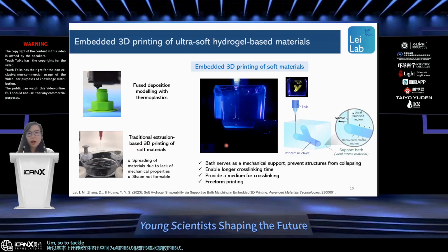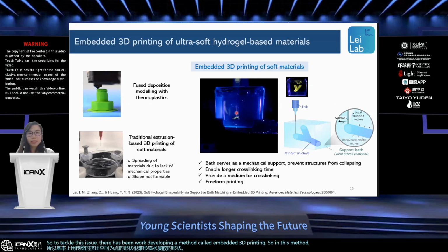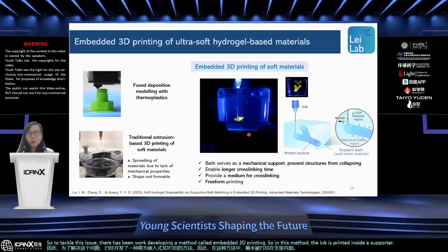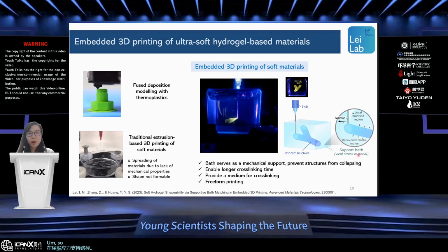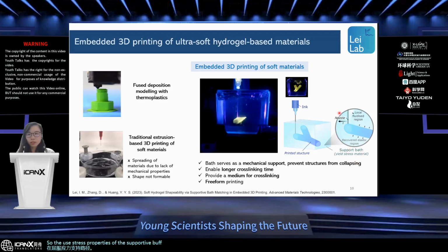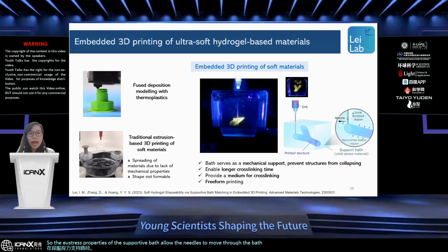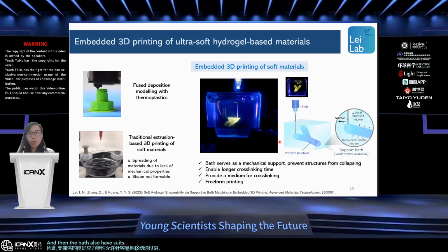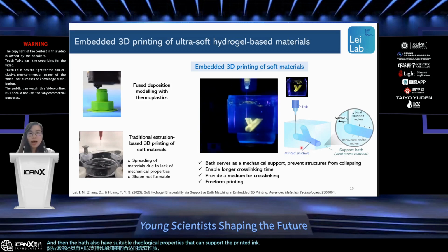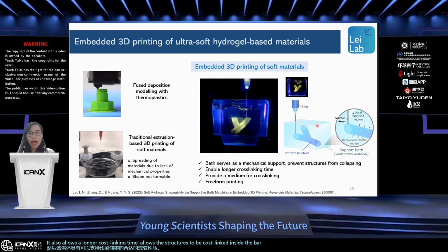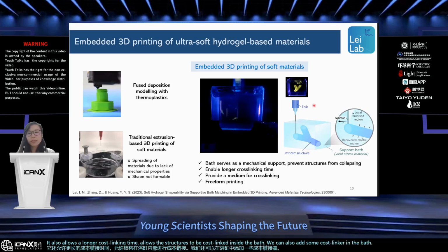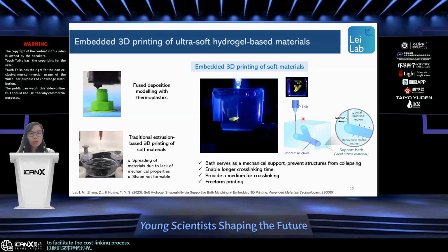So to tackle this issue, there has been work developing a method called embedded 3D printing. In this method, the ink is printed inside a supportive bath, a yield-stress supportive bath. The yield-stress properties of the supportive bath allow the needle to move through the bath easily. The bath also has suitable rheological properties that can support the printed ink. It also allows a longer cross-linking time, allowing the structures to be cross-linked inside the bath. We can also add some cross-linker in the bath to facilitate the cross-linking process. So this method can